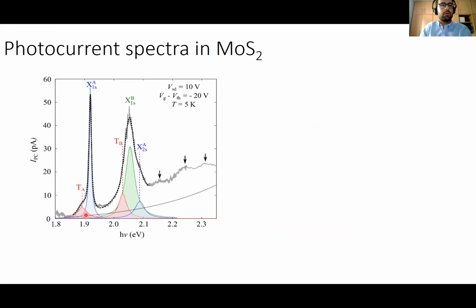Here we have a plot of a typical spectrum that we obtain in the monolayer MoS2 phototransistor using low temperature photocurrent spectroscopy. And here we observe that we have 5 spectral features plus an exponential background. We can fit our spectra very well.